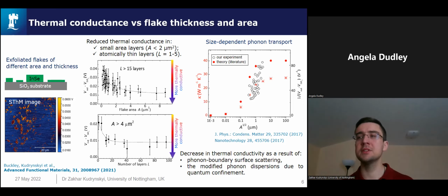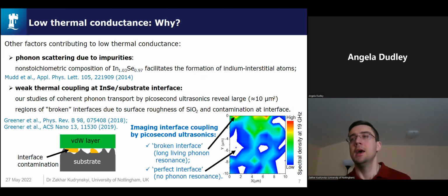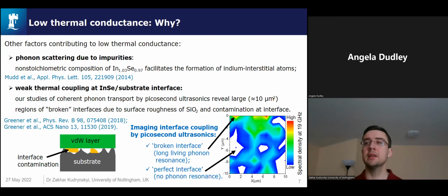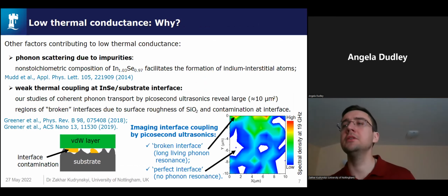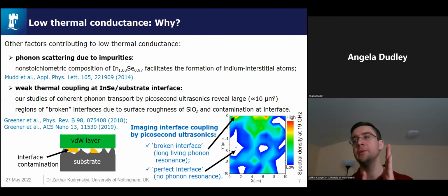The phonon coherence length tends to decrease proportionally with decreasing thickness, and phonon modes change only in few-layer indium selenide. Apart from that, there are other important factors contributing to low thermal conductance, including phonon scattering due to impurities such as indium interstitial atoms in our crystals. Also, the interface of 2D indium selenide with the supporting substrate can play an important role.